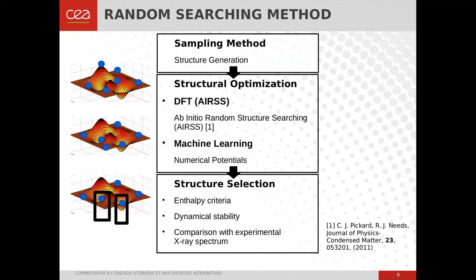To make this exploration possible, the algorithm enforces three steps. The first is a sampling step: generating different images of the system — different crystal structures. The second step is structural optimization, which consists in moving each initial point toward a structural minimum by modifying atomic positions and crystal geometry to minimize the energy. This step can be enforced only by DFT computations — this is the ab initio random structure searching method — or you can use machine learning potentials, which is the approach I investigated during my PhD. The third step is to select the most interesting structures using criteria like enthalpy, dynamical stability, or experimental information such as X-ray spectra.